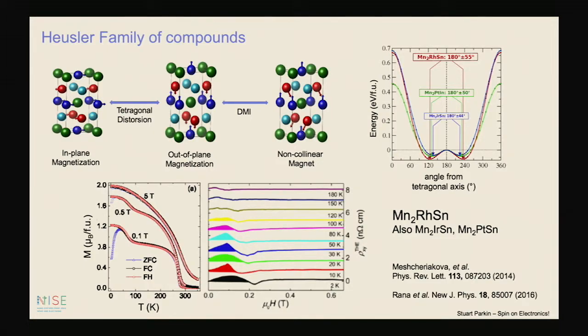And the work that led to this was that these materials, for example, manganese 2 rhodium tin or manganese 2 platinum tin, consist of structures in which you have alternating layers of manganese plus rhodium and then manganese plus tin, and they're ferrimagnetic. One layer is oriented with its magnetization antiparallel to the next layer. And there's a whole family of these materials. Magnetization looks like this. As you reduce the temperature, you see Curie temperatures close to or above room temperature. And we had some evidence from anomalous Hall effect that there was a topological Hall effect characteristic of anti-skyrmions or skyrmions in this manganese 2 rhodium tin material.